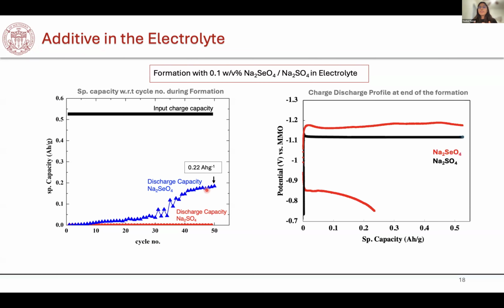And if we look at the polarization curves of both these electrodes, you will understand more clearly what's happening. When sodium sulfate is present in the electrolyte, there is no voltage plateau during the charging, and this indicates that the electrode is completely passivated, and all of the charge is going towards the parasitic hydrogen evolution reaction.